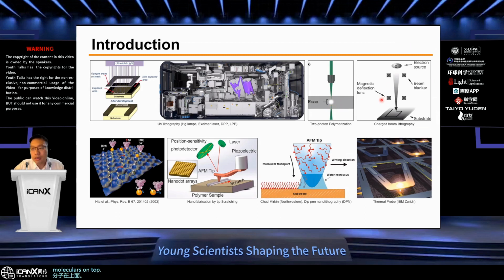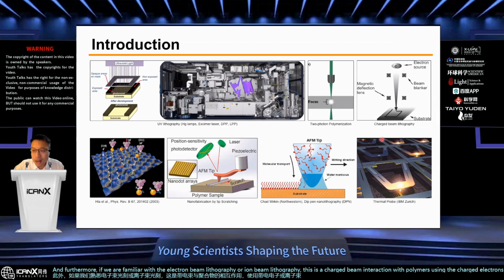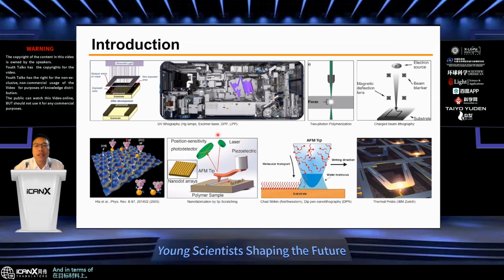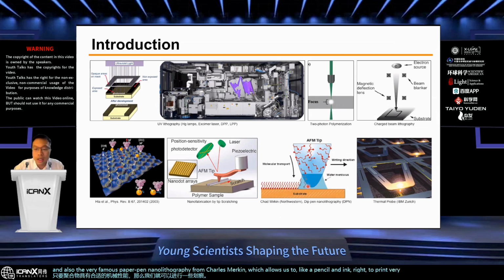molecules or polymers. And furthermore, if we are familiar with electron beam lithography or ion beam lithography, this is a charged beam interaction with polymers, using charged electrons or ion beams to create tiny structures on the target materials. And in terms of scanning probe-based fabrication, from the very beginning, STM is able to manipulate atoms in the lattice. And of course, with an AFM tip, we can easily think about scratching by a tiny tip on the polymers. As long as the polymer has suitable mechanical properties, then we can make some scratches. And also the very famous dip-pen nanolithography from Chad Mirkin, which allows us, like a pencil and ink, right, to print various molecules on the surface.